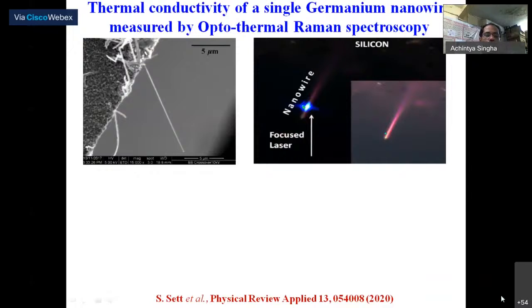So recently we did another experiment with a nanowire. This is a germanium nanowire again, grown as a suspended nanowire, suspended from the substrate. We did the same measurement as I said before, but at different points of the nanowire, which changes the length of the nanowire, and we measured the thermal conductivity. That measurement data is in very good agreement with other data measured with very sophisticated techniques. We did the diameter variation and length variation, got very nice results, and published them just recently in Physical Review Applied. Okay, go next.